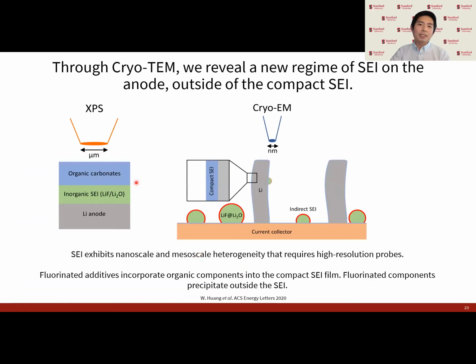And from this sort of relatively simple study, we can already learn a lot about the SEI. First, we can see that XPS can detect the chemistry of the SEI fairly well, which is what it's designed for. But for detecting SEI structure, it's fairly ineffective. Only using a high resolution method, such as this cryo-TEM method, can we start to get accurate pictures of the SEI on these battery materials.